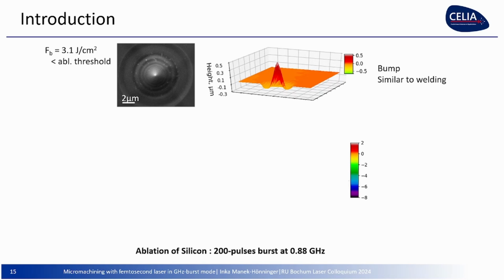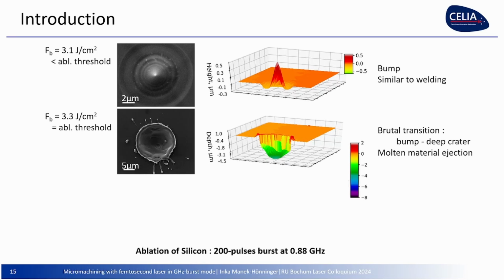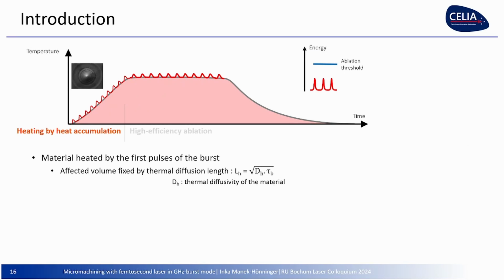So what is happening? This is the case of silicon. We have a burst where you still are below the ablation threshold. We form a bump like this, which is similar to welding, which you are familiar with. Then, if you are around the ablation threshold, we can explain it by accumulating heat during this phase, where we are still below the ablation threshold.